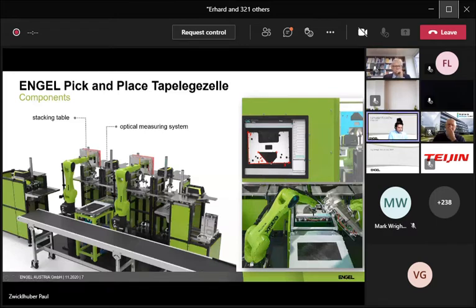By shape detection, edge and corner point detection, the exact position of the current tape at the end of arm tool can be determined. Now the system knows the current position of the tape at the end of arm tool and also the position of the previously placed tapes which are already on the stacking table. This allows building up a layup with almost no gap or no overlap. At the test setup, a placing accuracy of plus minus 0.2 millimeters could be achieved.